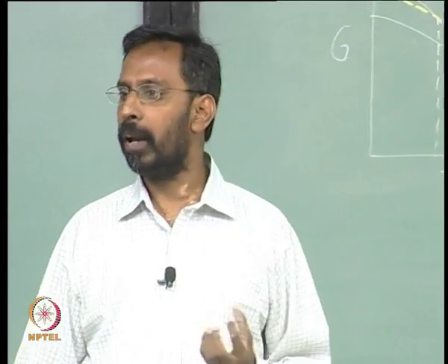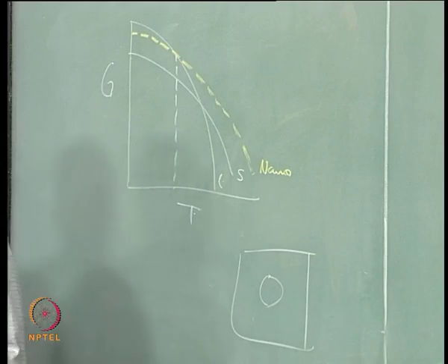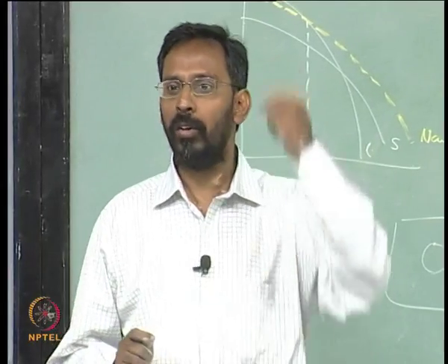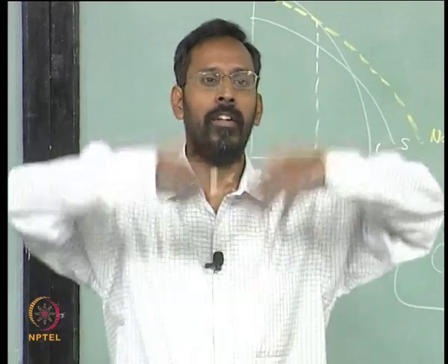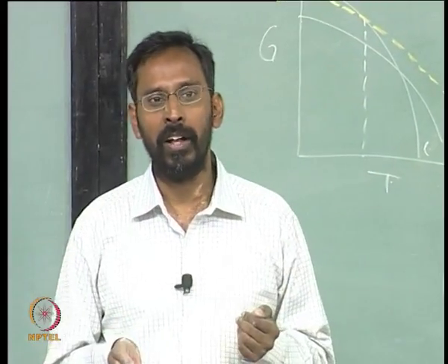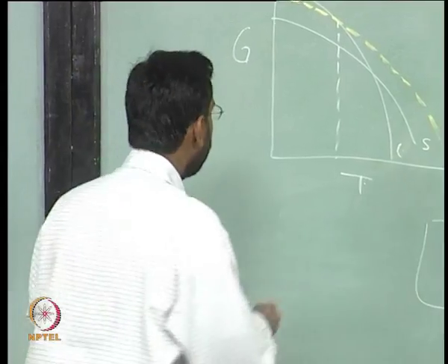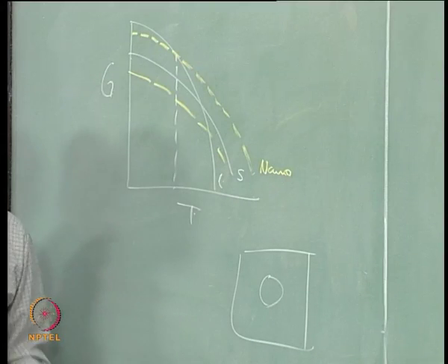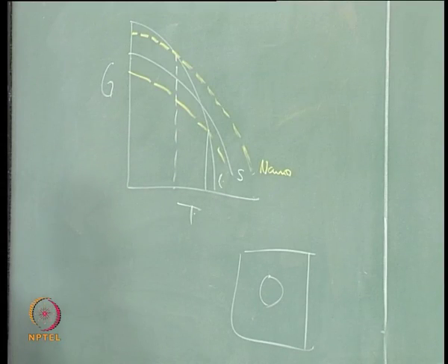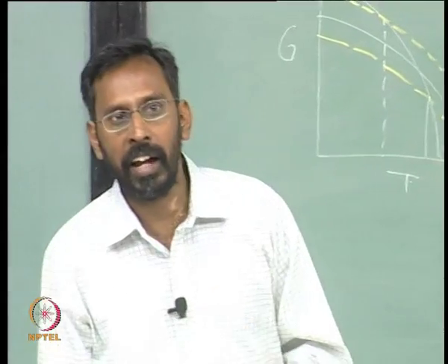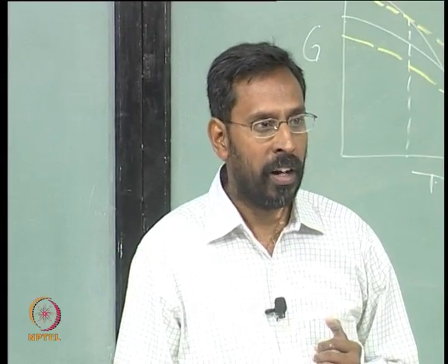The moment a pressure is applied, if you look at the Clausius-Clapeyron relation, whenever the delta V between solid and liquid shows a volume expansion on going from solid to liquid, under applied pressure the solid is more stable, because the solid occupies less volume than the liquid. So you will see the stability shifts, and the melting point goes up. Always you see this happening. Whenever you take an embedded nanoparticle, it melts at a higher temperature than its normal melting point. It is because of the pressure effects.